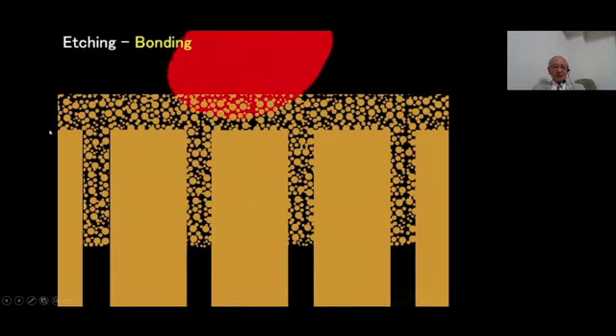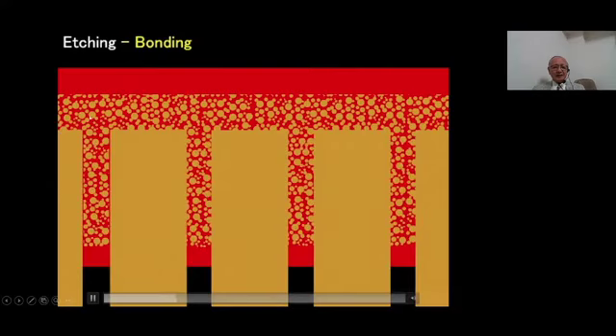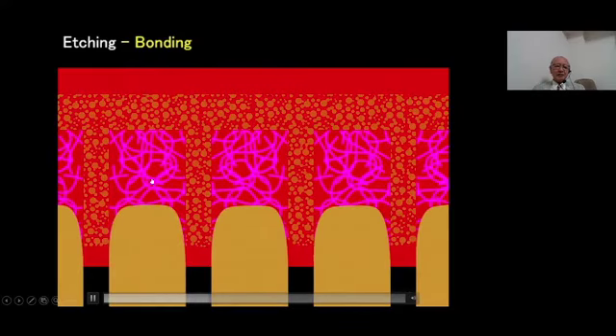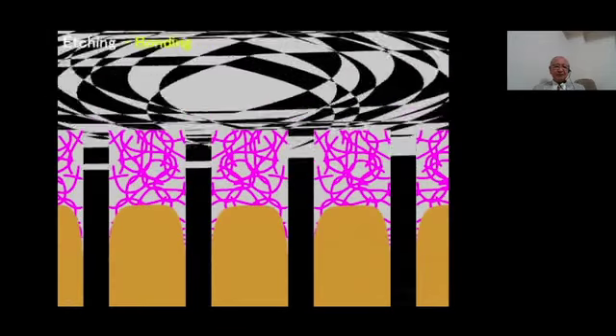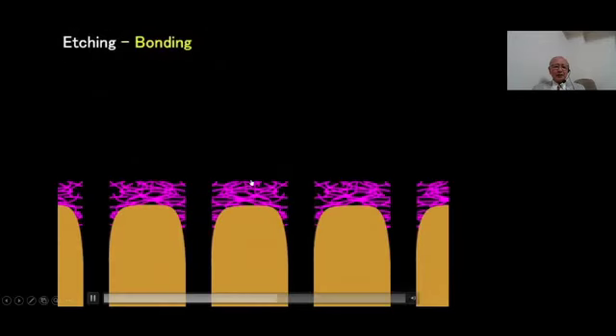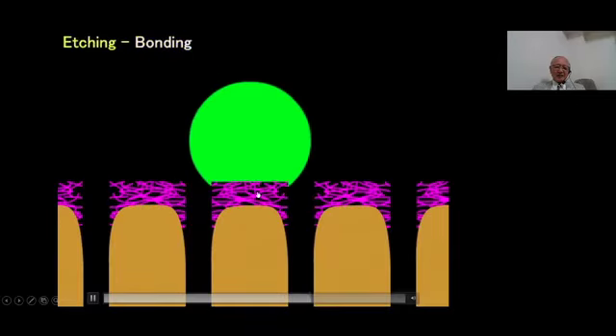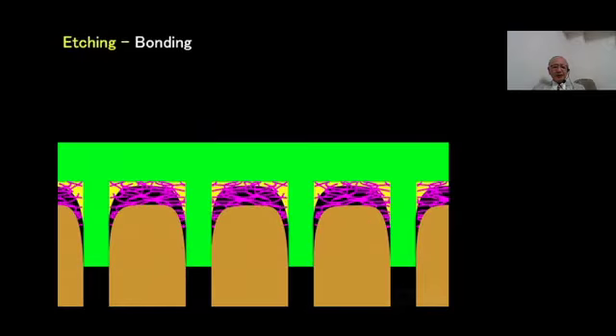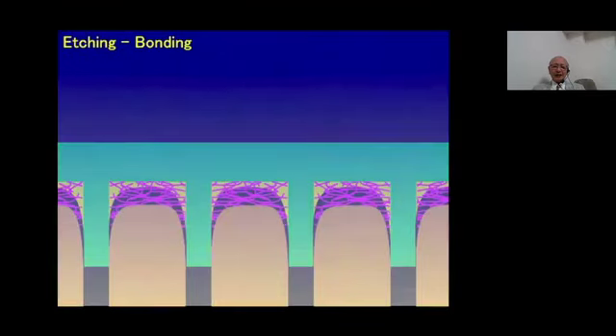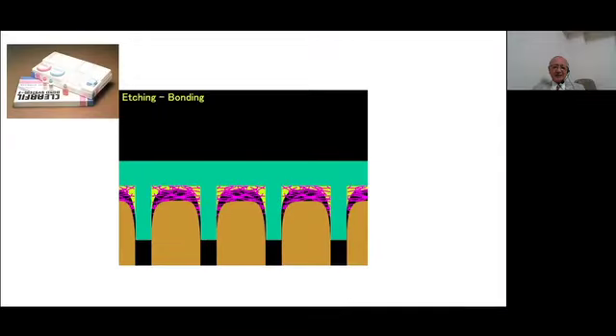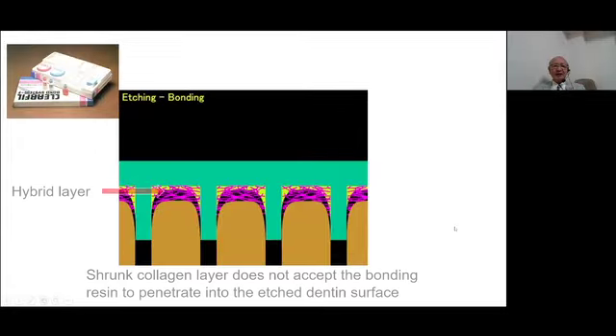Etching is done with phosphoric acid. This is a very strong acid. Very quickly the smear layer is dissolved and the surface of dentin is demineralized. Then the collagen layer is exposed, and by drying it shrinks. Onto that surface, if you apply the bonding resin, the bonding resin cannot penetrate into these shrunk collagen layers. That's why this layer looks like a hybrid layer. However, there are a lot of naked collagen fibers without penetration of the bonding resin. That's why the durability of the bonding was not so excellent.